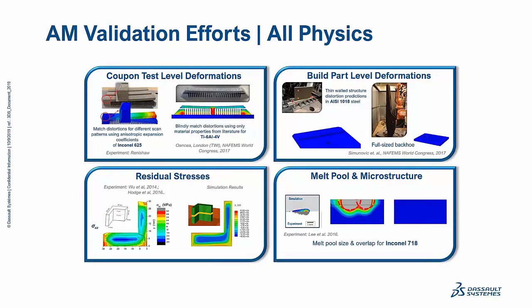Now, when I'm talking about all the things that we can do, here are some interesting validation examples that are real-world parts that were run with our simulation framework. So yes, we can of course do simple analyses, coupon test level deformation simulations, like these ubiquitous cantilever bridges, and we have very good agreement between the deformation and the print simulation in these cases. This is a very simple and commonly used structure, but as we learned, we are very good at predicting residual stresses, and here's an example of residual stress simulation done by a researcher called Wu, where the simulation and the experimental data have extremely good agreement, allowing us to use this kind of simulation in predictive mode to see what is happening and predict possible issues with the print.